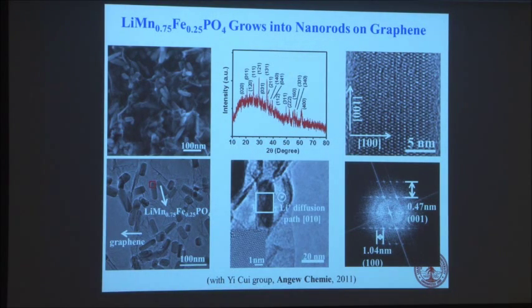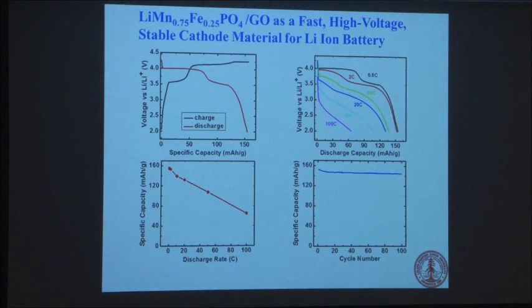This example here is these nanorods I mentioned, grown on graphene. Because they're such small rods, ions can go along the radius direction of the rods. And the electron transport is very fast because it's right on top of a conductor. And we found that they work very quickly. In this case, the discharging you can do at a very high rate. We went all the way to 100 C, and this material can be discharged very quickly.